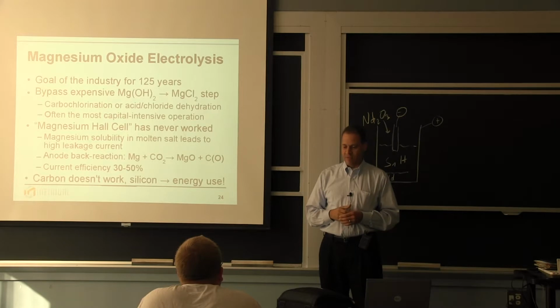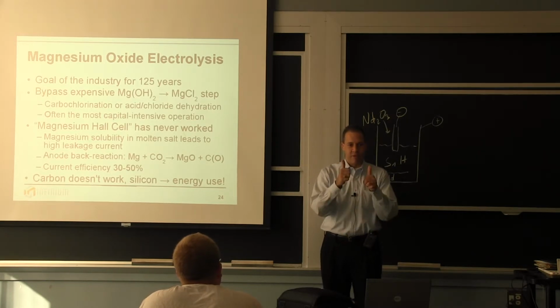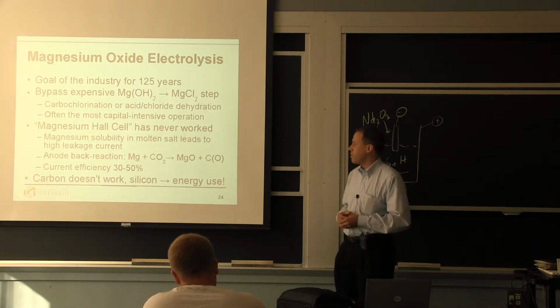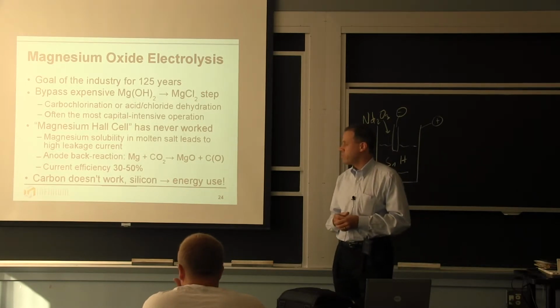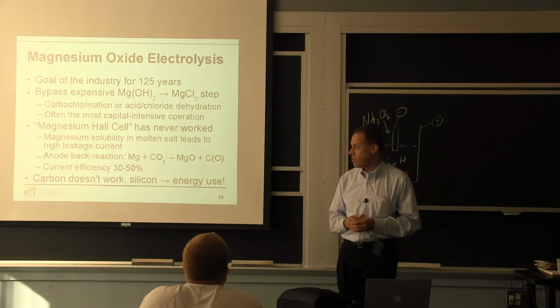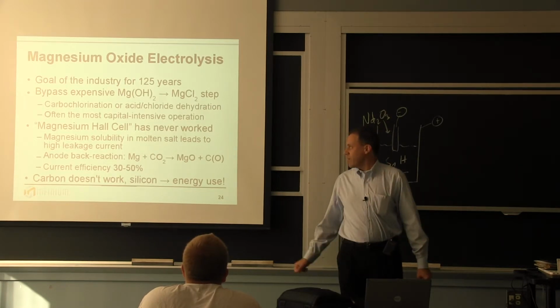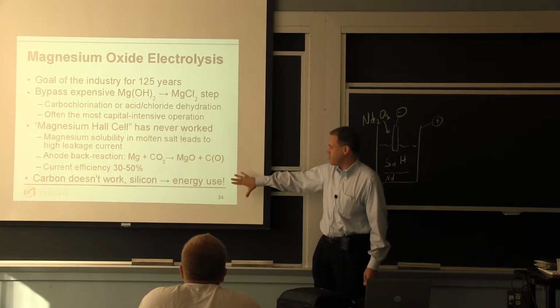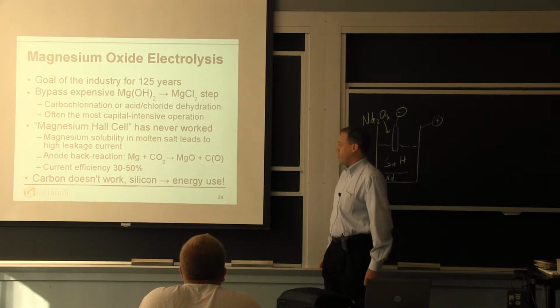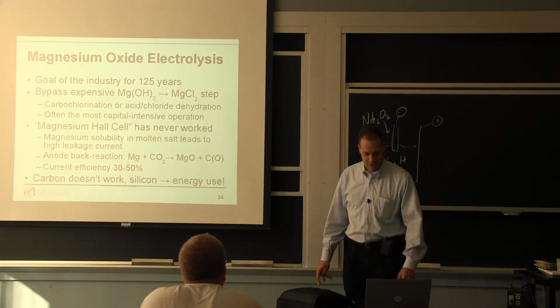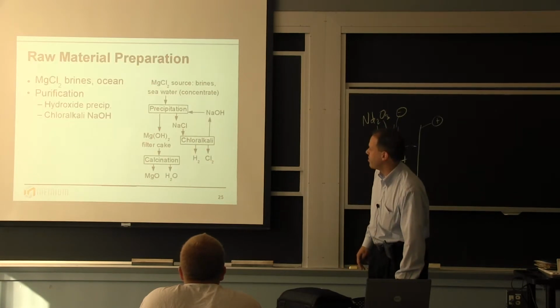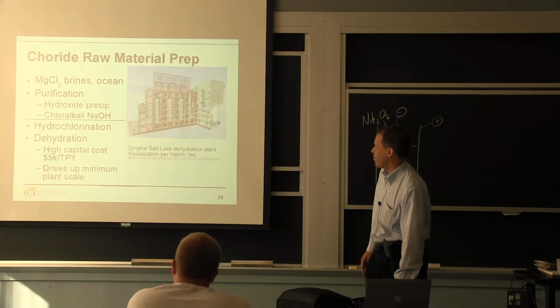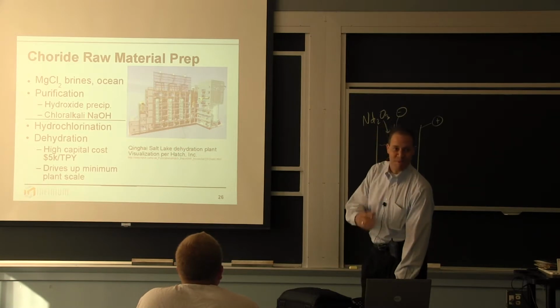It's a lot more difficult than it sounds, because you have to manipulate the pressure in order to avoid hydrochloric acid evaporation from your cell. It's the most capital-intensive operation in production of magnesium. So for this, the magnesium Hall cell has never worked. It's complicated why. Carbothermic reduction doesn't work. Silicothermic reduction leads to very high energy use, as I mentioned. So this is why magnesium chloride is very expensive. Yeah, trust me, read up on it if you're interested.